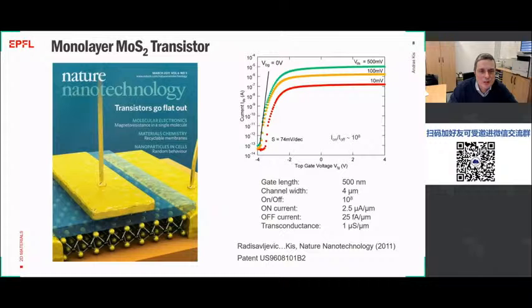So you cannot really use it that easily to make standard semiconducting devices, logic circuits, and pretty much everything that we're used to working with in electronics, because for that you need a band gap. MoS2 was the first example of a 2D material with a band gap, a 2D semiconductor, and we made the first working transistor based on this material, with a very high on-off ratio of 100 million and a very good switching slope. The more important thing about this result was that it showed that there are other materials that people knew of, but were not really studying, that can be used to make devices, and not just graphene and boron nitride as the substrate.